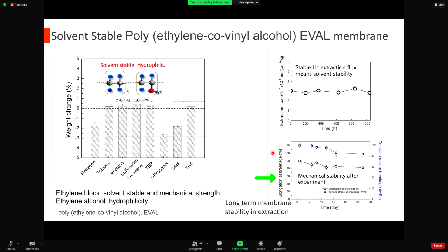And this polymer is also very resistant to a lot of solvents. We use DMSO as the solvent for this polymer, but THF, DMF, alcohol, toluene, benzene, and acetone, it is very resistant to. We have done a stability test for 1,000 hours by checking the lithium extraction flux after the membrane is taken out of the organic extractant. It shows a very stable performance, and the mechanical stability of the EVAL membrane is also perfect.